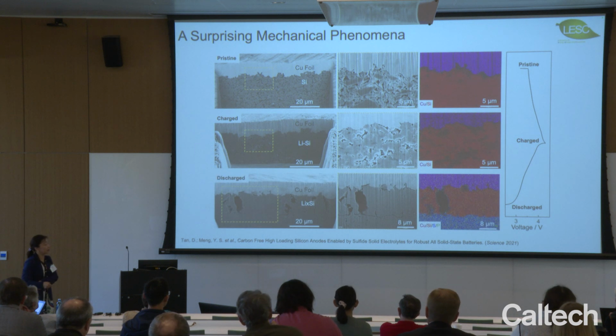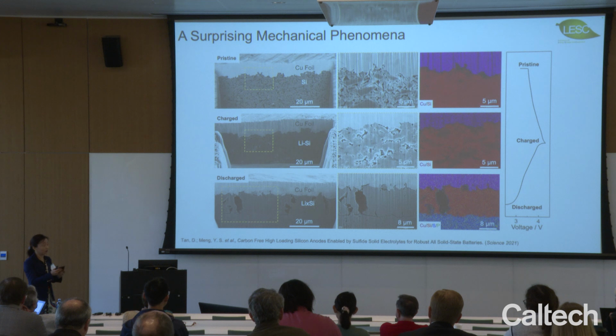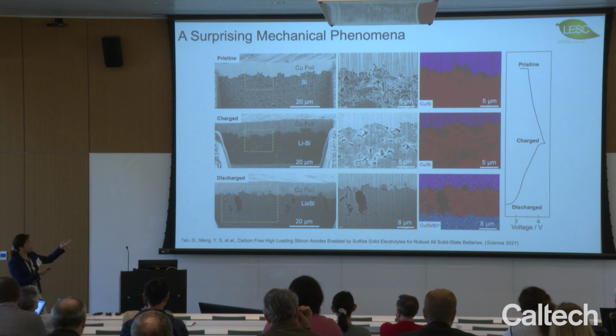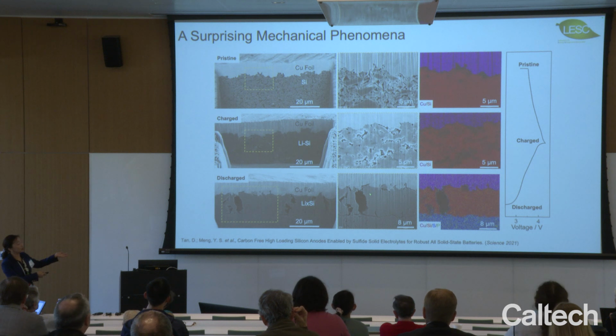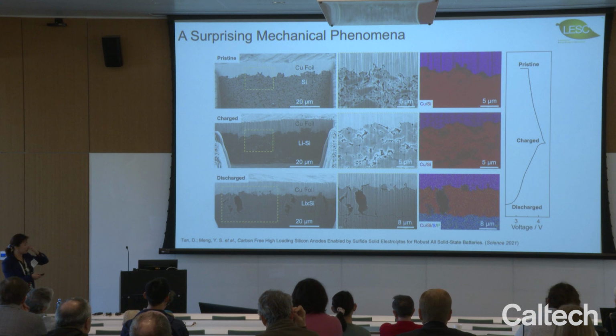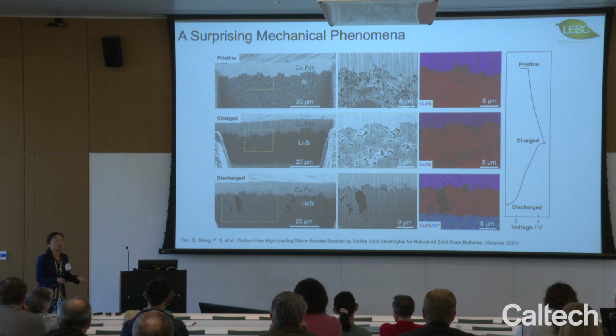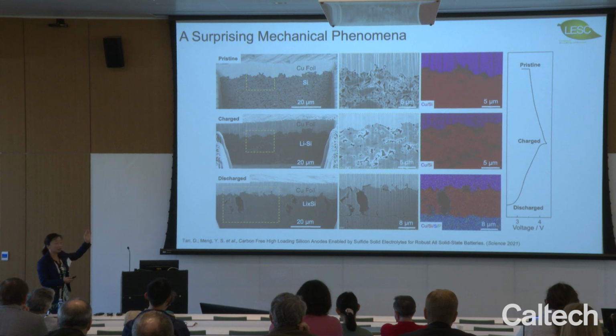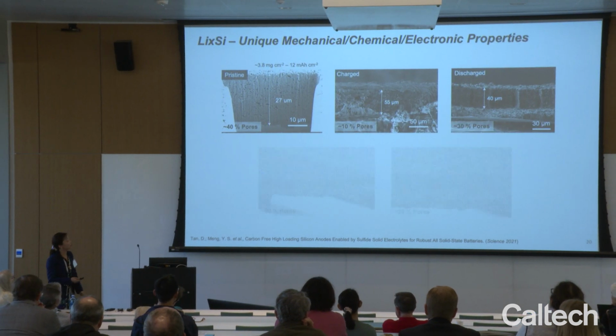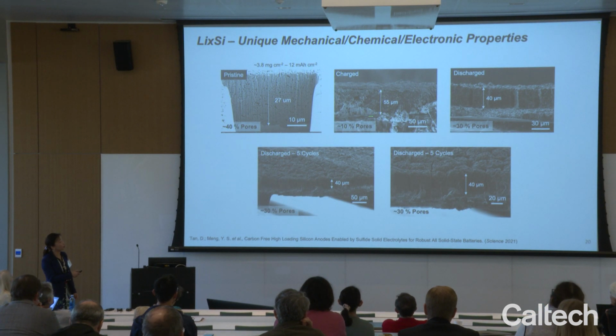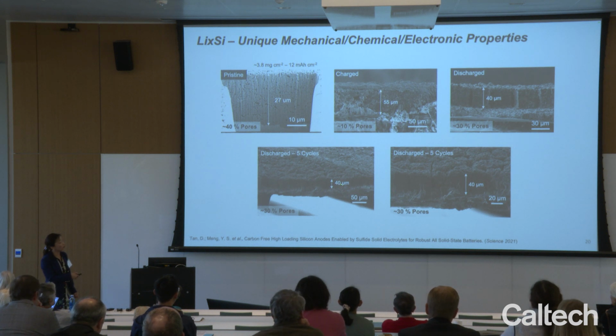Now, this is a reminder to myself, I should wrap up. So when you actually take lithium back out, the pore formation is vertical, and the paper has been out for 2 years, and we still couldn't fully understand what happens in the pore formation during the discharge process. I just want to show you the initial volume expansion is real. You have almost 100% volume expansion, but when you discharge, you form a stable structure with 30% pores, and the stable structure actually does not change upon further cycling. This is something we created in the solid-state cells, which you will not see in the liquid cells.